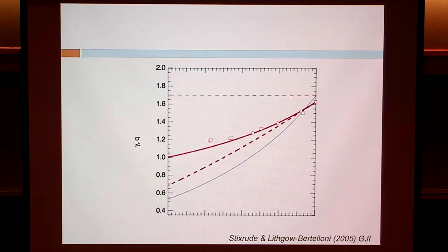Okay, so the dashed lines are Q. So if Q is constant, then the Grüneisen parameter decreases very rapidly on compression, much more rapidly than the ab initio theory indicates. And so this is an example of how we can use ab initio theory to put constraints on the functional form of the fundamental thermodynamic relation.